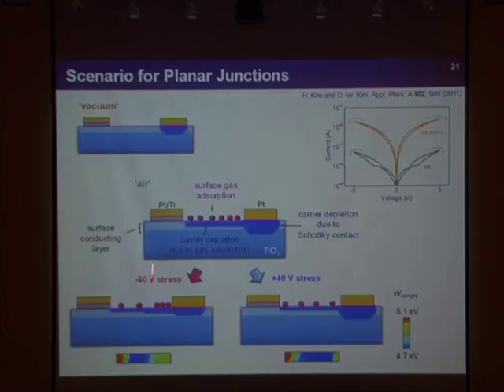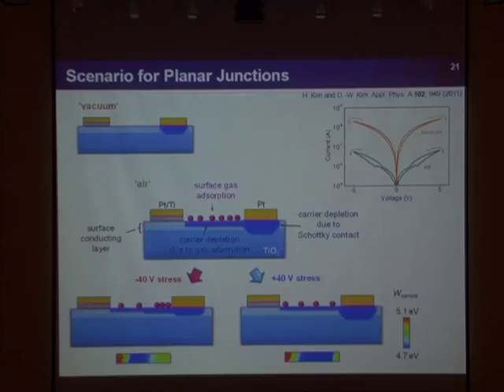So this is a scenario to explain all the experimental results. This is the initial sample stage. Actually, we anneal the sample in a forming gas environment for a short time, so only at the surface is the carrier concentration high—it's like a single crystal thin film.